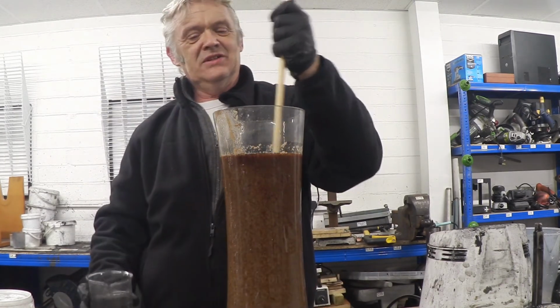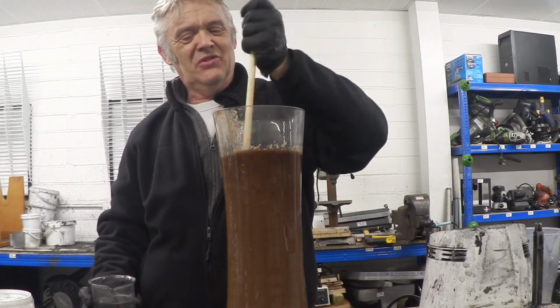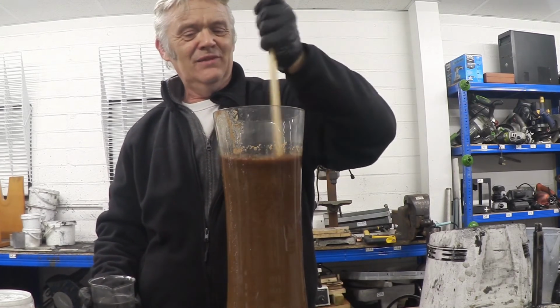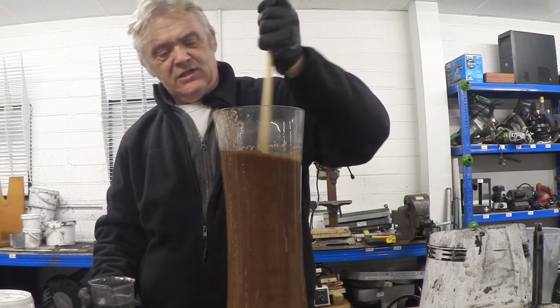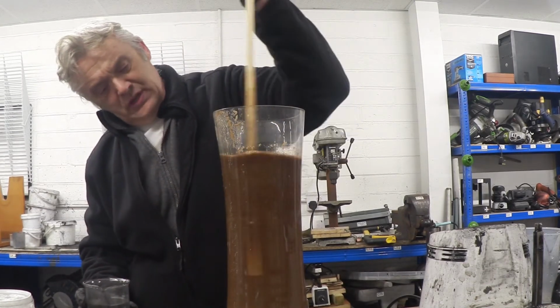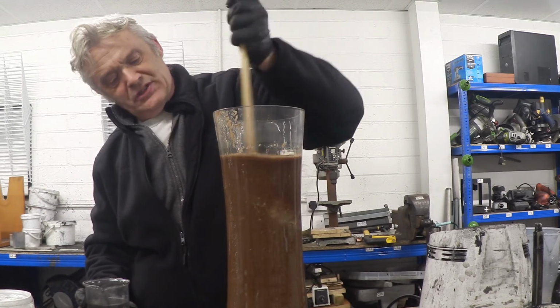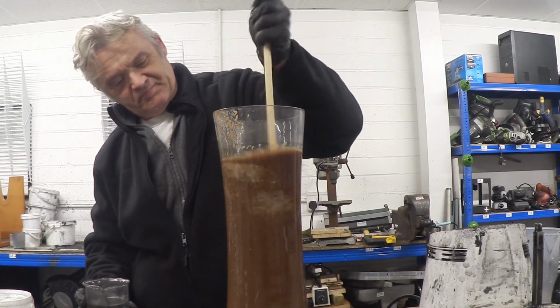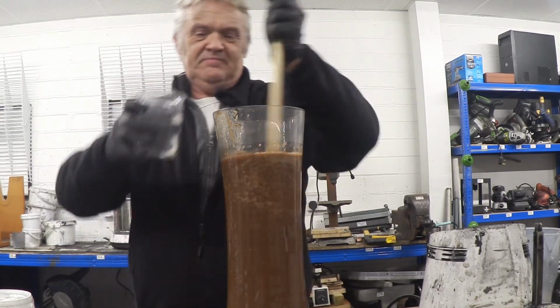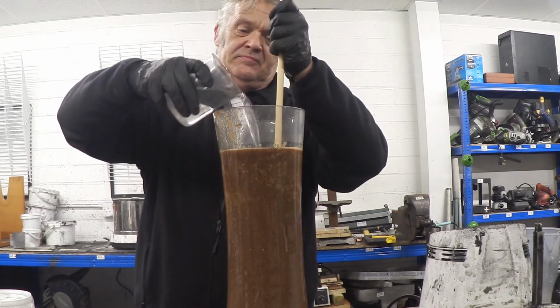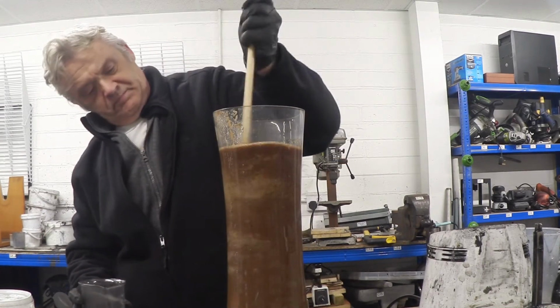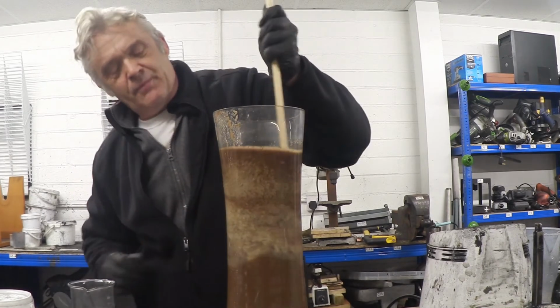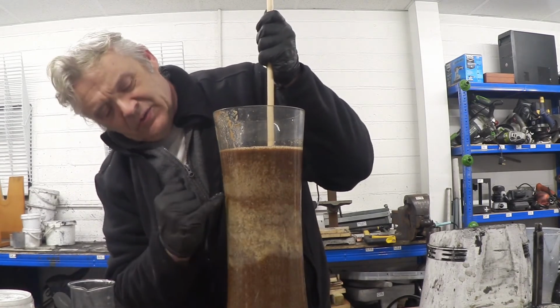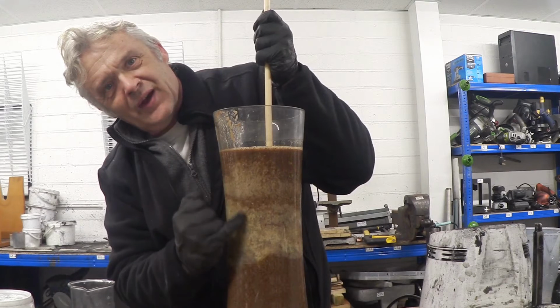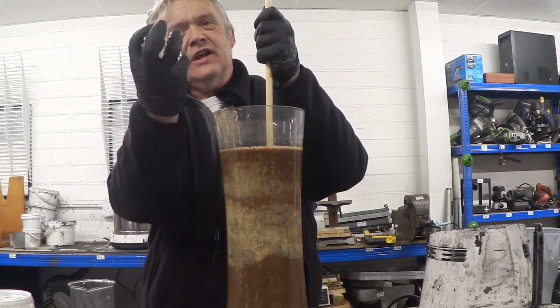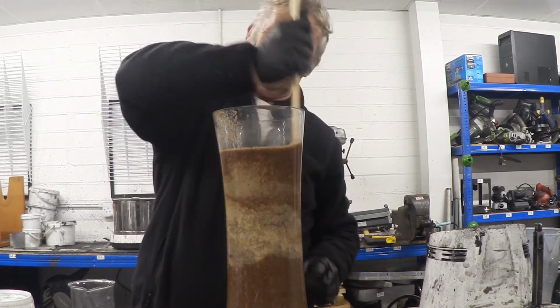Now we're adding an acid to an alkali, so don't chuck the whole thing in there or you really will be sorry. And as it gets acidified, you should be able to see that it's beginning to agglomerate, which is kind of cool. See that? It's going from the brown colour, which was a tannin, to this kind of whitish colour, and that whitish colour is where the casein is curling up around the hemp fibre.